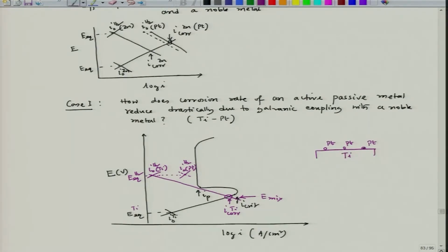So, these are the zones where platinum is locally present. This provides surface for hydrogen evolution, and the exchange current density of hydrogen evolution on these platinum surfaces will be much higher than the hydrogen exchange current density on titanium surface.